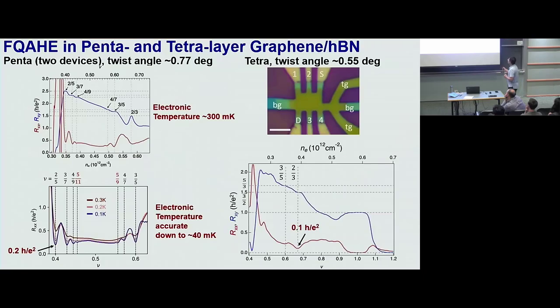And we made another sample, which is a tetralayer graphene, and it's a standard Hall bar, and this is probably at the temperature of like 200 or 300 millikelvin. You see the integer quantum anomalous Hall state, and the fractional quantum anomalous Hall state has 3/5 and 2/3. In this case, the 2/3 dip is as small as 0.1 h over e squared. So this FCI physics is repeatable in 4-layer, 5-layer, 6-layer if you combine all the community's effort.